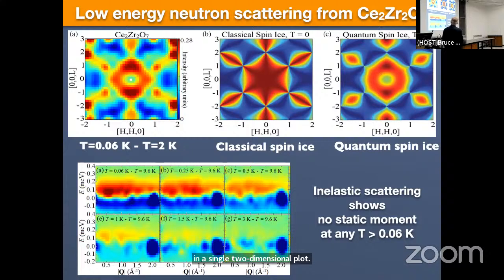Okay, and so this is energy versus the modulus of momentum. And actually, this is data that shows a temperature difference. So in this case, 60 millikelvin minus 10 Kelvin, and then 0.25 Kelvin minus 10 Kelvin, and so on. And we're going to identify the net magnetic scattering, or the net scattering of interest, by any region where there is more scattering at low temperatures than there is at high temperatures. So anything in red is what we're really interested in.